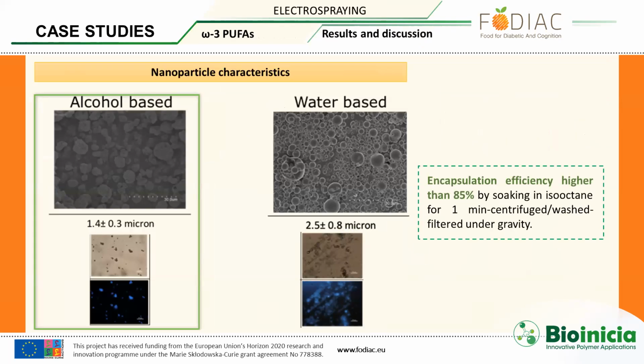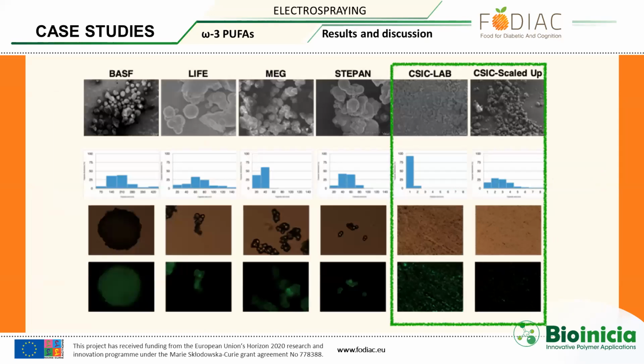We have encapsulated those omega-3 fatty acids in different materials, alcohol-based materials or water-based materials, and the particles obtained are in the micron range, around 1 or 2 microns, and the encapsulation efficiency was quite good, around 85%. If we compare our particles with the commercial ones, we can see that our particles are very small, even for the scale-up process.